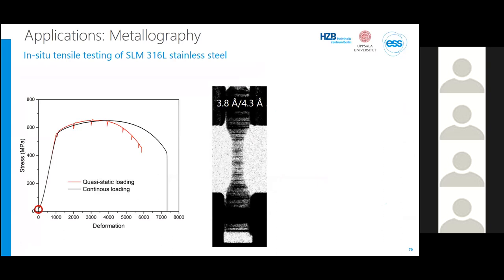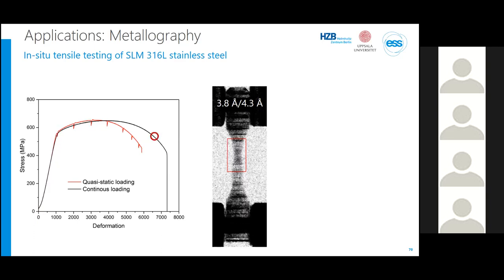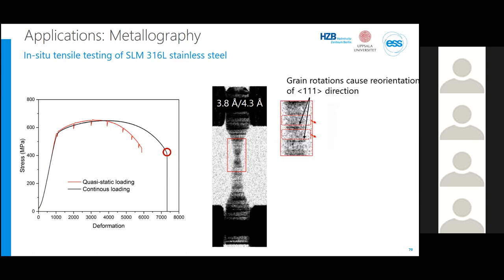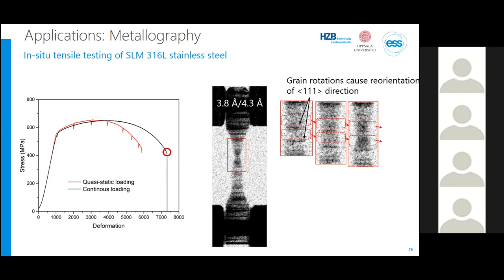And then again, the neutrons compared to EBSD are very powerful for in situ studies. So finally, we did in situ tensile testing of these samples. And here you can see a sample built with a Z-scan strategy being loaded in tension. So you should watch the region in the red rectangle and how it changes the gray value. And what we observe here is a grain rotation and reorientation inside this area.